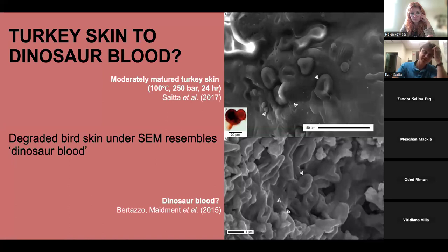And so there's all sorts of interesting avenues you can go with thermal maturation, some of which are less expected. So this was sort of a surprise result. If you take turkey skin and you moderately mature it such that it doesn't completely break down but is largely degraded, and then you look at that under the low pressure conditions of a scanning electron microscope, I observed these folds and pocks and blebs, which were very similar to what had just been published at the time of putative dinosaur red blood cells, which also appear to be just folds within a continuous organic material, pot marks, blebs.